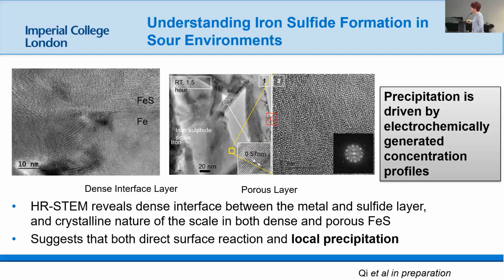What we're seeing here is a combination of surface reaction and local precipitation. And this local precipitation, really, that we're interested in is precipitation of a system driven by an electrochemically generated concentration profile. So we normally think of supersaturation in chemical systems. You know, everyone does a sugar experiment and lets it cool down and it precipitates out. Here, what we're finding is in electrochemical systems, it changes locally the concentration profile and locally will supersaturate. And depending on those local supersaturation conditions will give you different types of structures.